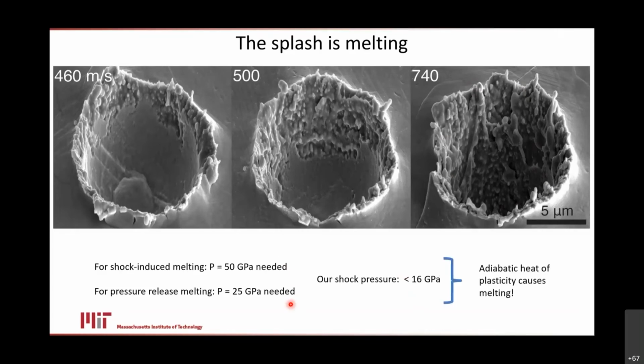Why did it melt? I'm going to spare you some details here and tell you that our shock pressure is actually pretty low. It's only 16 gigapascals, so we don't think this is a pressure or pressure release related melting. This melting is because of plasticity. We are simply deforming this thing so fast and so hard that we are adiabatically heating it up to the point that it melts.